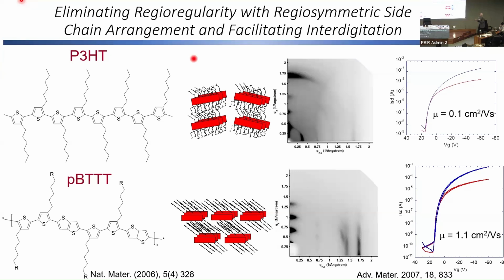Well, let's have a look at the thin film morphology. So here, this is P3HT. This is a 2D GIWAXS image. And you can see the reflection in the out of plane direction now kind of arcs a little bit. It's not spherical like in the bottom. Whoops, sorry. Down here. You can see here that the intensity of this reflection is much more spherical and much tighter. So that means there's no off-axis misorientation. So these polymers are really beautifully ordered and beautifully oriented in a thin film.